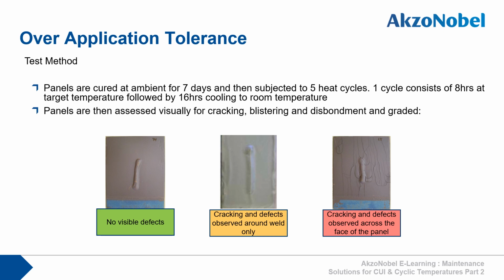As a way to demonstrate 2340 UPC's resistance to cracking due to over-application, a detailed test program was carried out by AkzoNobel. In this program, panels containing a weld are cured at ambient for 7 days and then subjected to 5 heat cycles. One cycle consists of 8 hours at the target temperature, followed by 16 hours cooling to room temperature. Panels are then assessed visually for cracking, blistering, and disbondment and graded. Green, no visible defects. Orange, cracking and defects observed around weld only. And red, cracking and defects observed across the face of the panel.